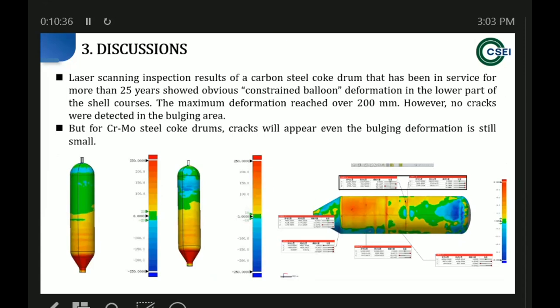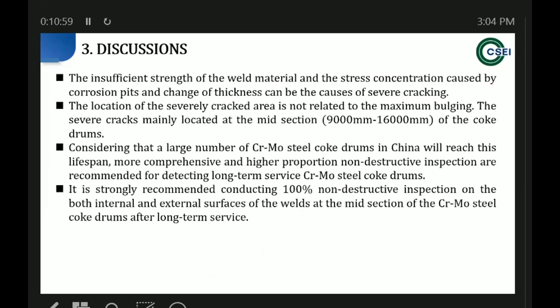And we can see the laser scanning inspection data from the carbon steel coke drum, and the maximum deformation can reach over 200 millimeter. However, no cracks were found in this bulging area. For the chromium molybdenum steel, the cracks appear even when the bulging deformation is still very low. And we can also conclude that the insufficient strength of the welded material, the stress concentration caused by the corrosion pit, and the change of thickness can be the causes of the cracking. It also indicates that the severe cracking is not related to the maximum bulging and is located at the middle section of the coke drum.